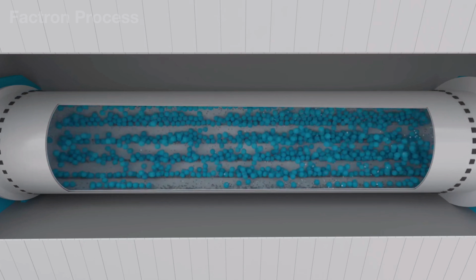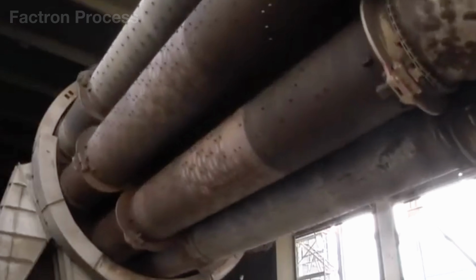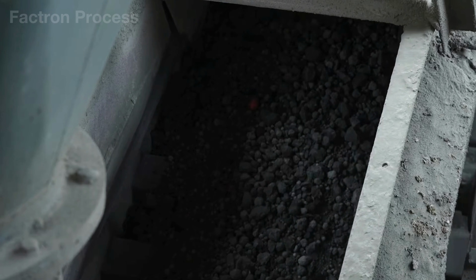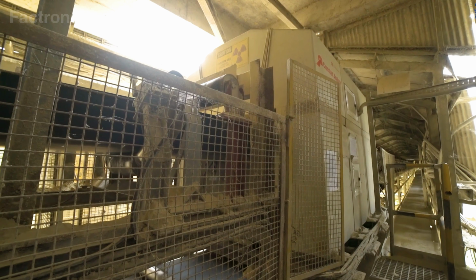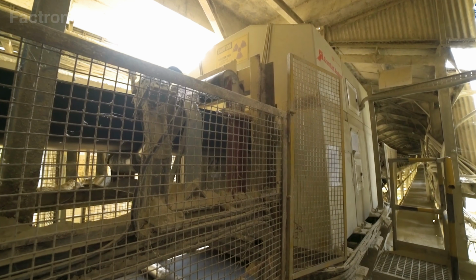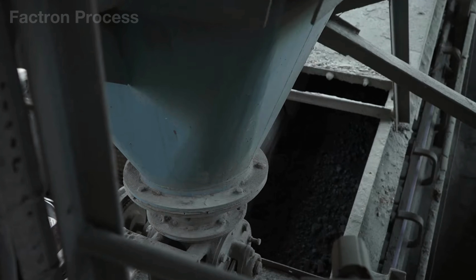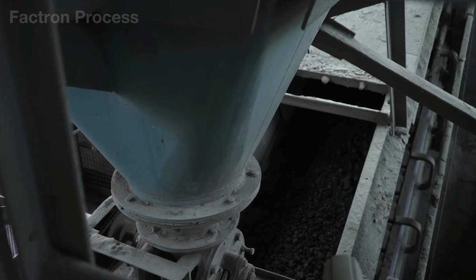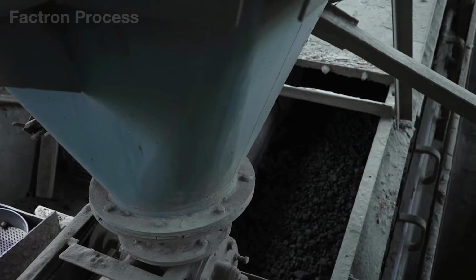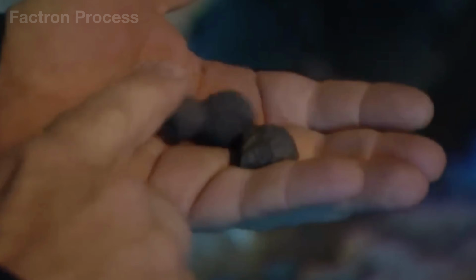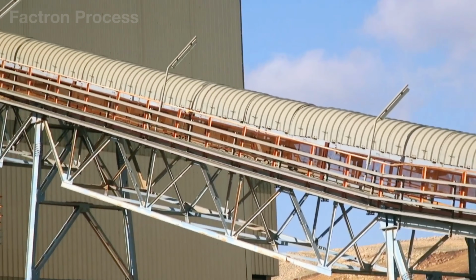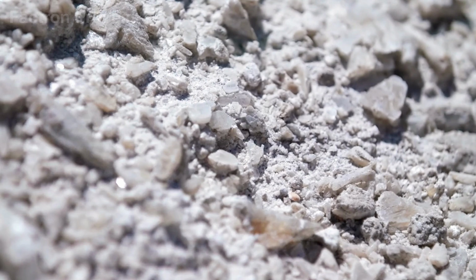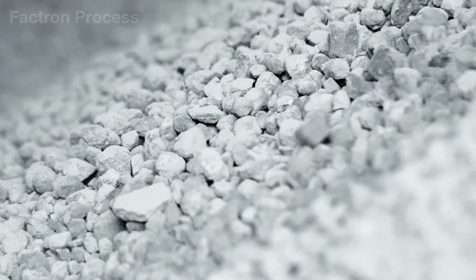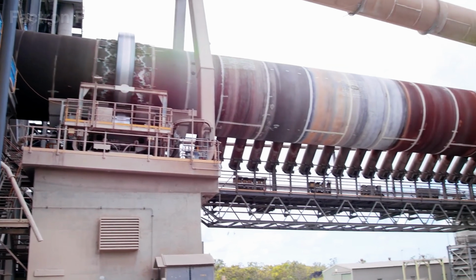What makes this system particularly effective is that the enormous amount of heat is not wasted. After absorbing thermal energy from the clinker, the air is heated to several hundred degrees Celsius and is then recirculated back to the rotary kiln and calciner to support fuel combustion. As a result, the grate cooler not only cools the clinker, but also recovers a significant portion of the heat that was just generated, improving energy efficiency and helping the entire production line operate more efficiently and consistently.